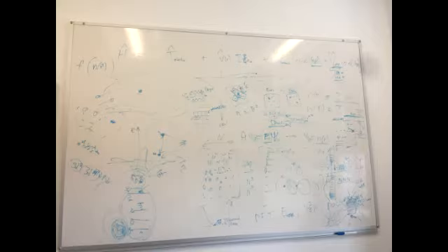Alternatively, maybe somewhere very close in energy, you get a crystal structure which is a perfect cubic structure. And then lithium just sits here and maybe it can hop, but maybe this barrier of hopping is too high. So all of these types of calculations can be done. There is actually a lot of stuff already done for single, maybe even for binary materials. So there is a website called Materials Project, and it actually was started explicitly for lithium-ion batteries. You have to register, but it's still free for use. Materialsproject.org.